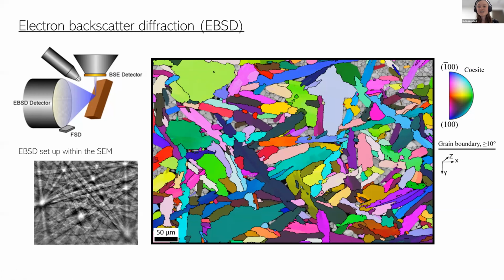So you can get grain size information from this, local, broad crystal preferred orientations, and also any kind of local distortion to the crystallographic lattice. So here we've got an example of an EBSD map collected for one of those samples. These are chunky sections of the coesite, and then you've got a band contrast image on the back, we've got all of the quartz, and each of these colors represents a different orientation of the coesite. So we can get an idea of the grain size, but we're interested in deformation, so we want to look at any internal distortion in either of these phases during the transition.